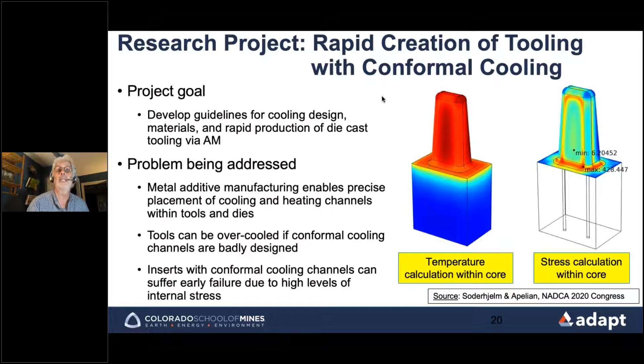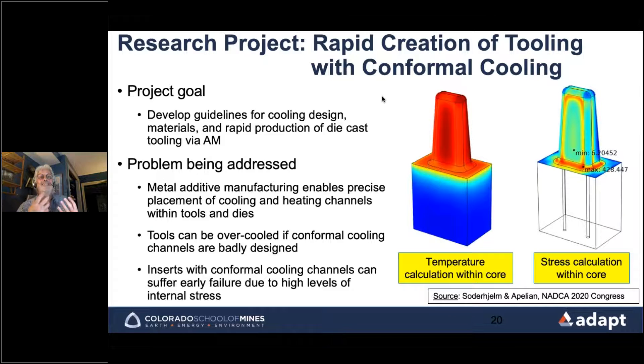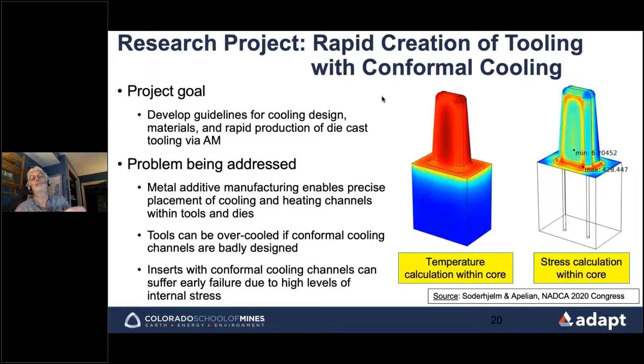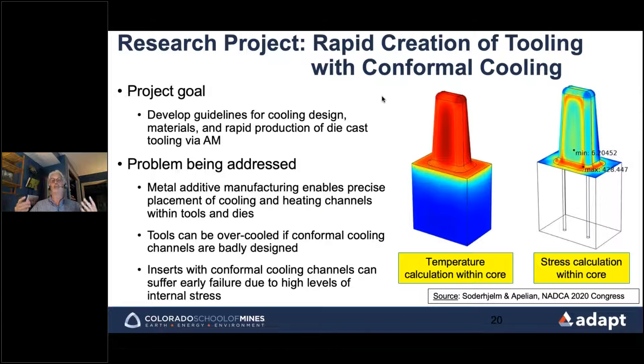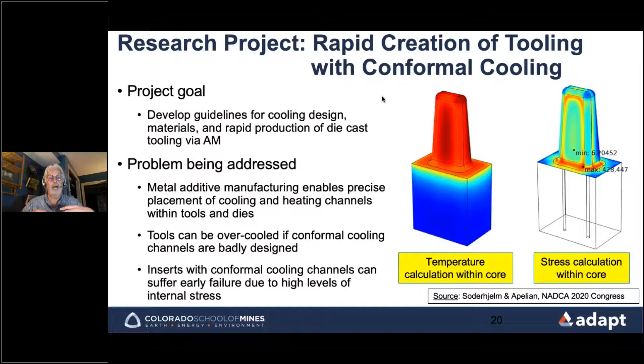A research project by Carl Soderhjelm and Daren Apelian, recently moved from Worcester Polytechnic Institute to UC Irvine, aims to develop guidelines for the die casting industry on using additive inserts — specifically how close cooling lines should be to the die surface and to each other. They found that when conformal cooling was first applied, people over-cooled inserts; now they're backing off. Carl is also doing stress modeling to look at high internal stress that has caused some early failures. This is a five-year project funded by the Department of Defense.